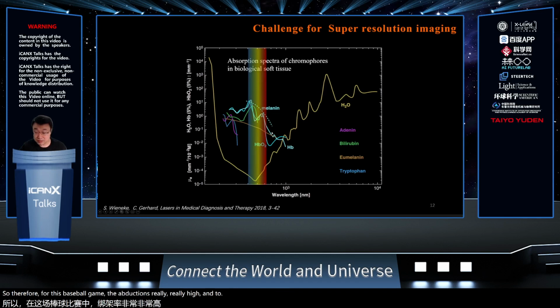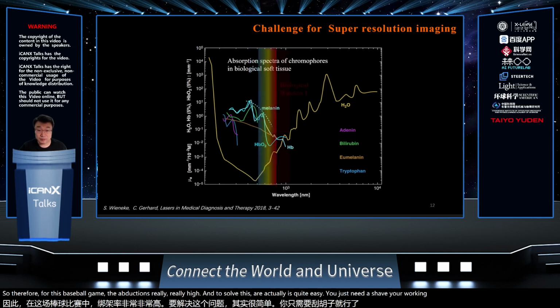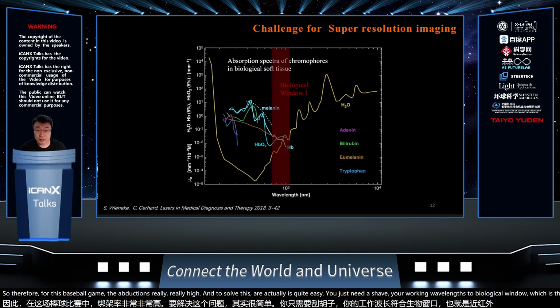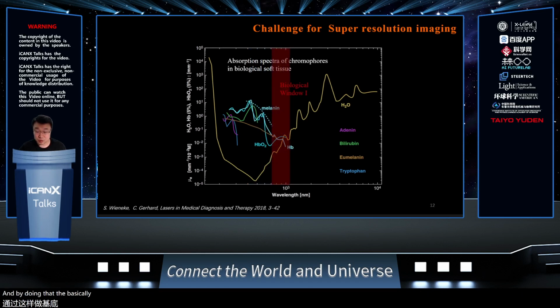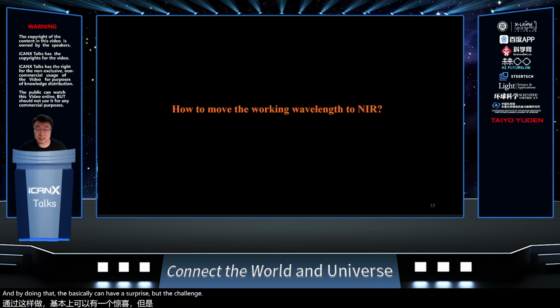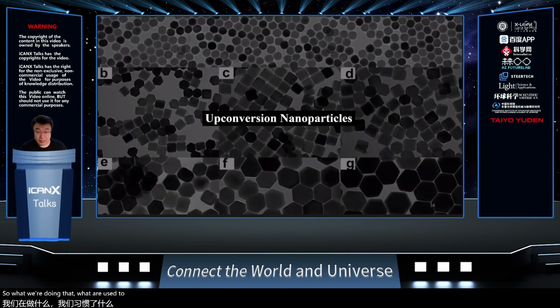To solve this one, actually, it's quite easy. You just need to shift your working wavelengths to the biological window, which is the near infrared range. And by doing that, you basically can have super resolution. But the challenge is how can we do that? Because currently only a few types of near infrared dyes work really well. So for doing that, what I did is use upconversion nanoparticles to solve this problem.